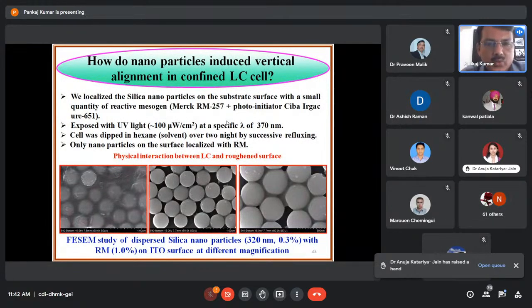The cell was dipped in hexane solvent over 2 nights by successive refluxing. Only nanoparticles on the surface localized with the RM. So I would like to say here, initially the silica nanoparticles were mixed with the liquid crystals, and reactive mesogen was mixed. Then because reactive mesogen was there, it was cured with the help of the irradiation of the UV light. So all the nanoparticles were deposited on the substrates. Then we refluxed the cell, we dipped the cell in hexane to reflux the liquid crystal materials, and after that we can see only nanoparticles on the surface localized with the RM.